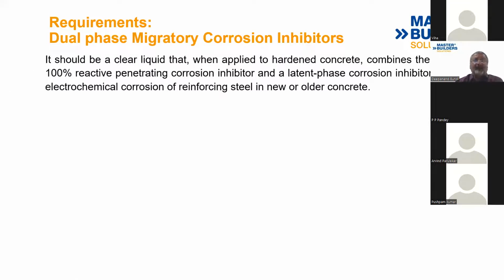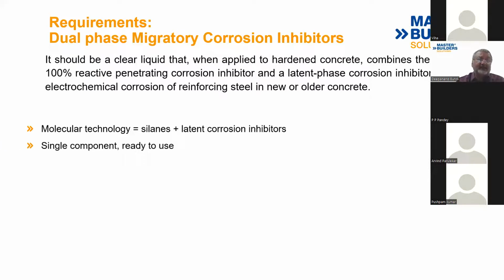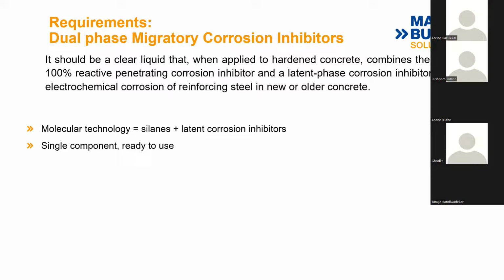What are the requirements of these dual phase migratory corrosion inhibitors? The first thing, as I said, should be a clear liquid and combines the power of a reactive agent, a corrosion inhibitor, and a latent phase inhibitor. That's when it goes inside, it should be able to penetrate and protect the reinforcement bar. So basically, this is a nanotechnology which combines the benefits of silane. Silane has a very small molecular size as compared to other coatings or paints, and combined with latent corrosion inhibitors, it remains active inside the pores of the concrete and still remains even if it cracks at a later stage. Single component, nothing to mix, just open the container, apply it. Very easy at the site, because we have challenges in application.